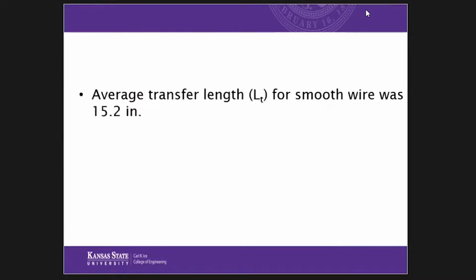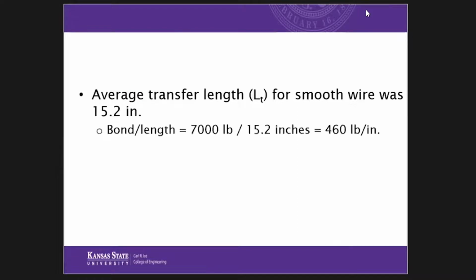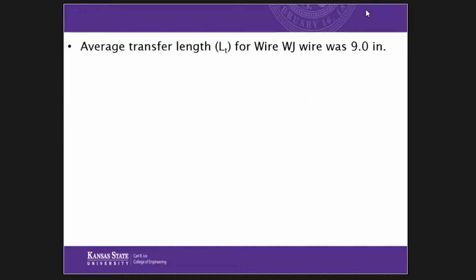So let's take a look at the smooth wire. That had an average transfer length of 15.2 inches. I mentioned we tensioned these wires individually to 7,000 pounds. So that 7,000 pounds, we divide by 15.2 inches, we're getting an average bond per length of 460 pounds per inch. And that's primarily due to the Hoyer effect. When we stretch that wire, it gets smaller in diameter. And then when we release it, it wants to get bigger, so it's providing a normal force. And it's based on the frictional characteristics of the wire.